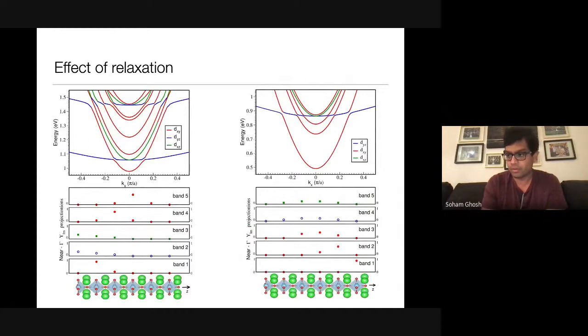Now, one of the ways you can get to these subbands is to relax the system. When you put strontium oxide and lanthanum aluminate together, or if you only have strontium oxide, the moment you create a surface, the atoms on the surface relax, and the electrons change their states due to the relaxation. So on the left are the bands for the electrons on a non-relaxed system, and on the right is the same system, but I have allowed the simulation to relax the atoms. And you see the effect of relaxation is that the bands become much more non-degenerate. The electron wells become much more defined.